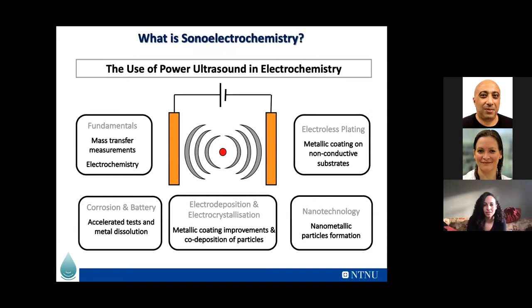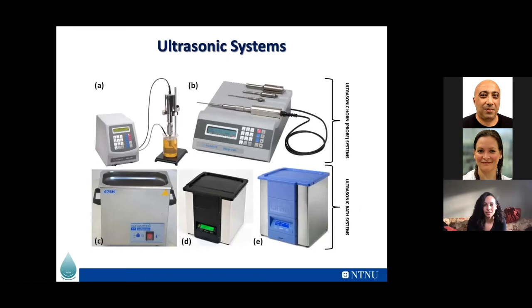There's also another area where you could use ultrasound, in electrochemical engineering and electrochemistry. For example, we looked at mass transfer measurements. You could also use ultrasound to get better plating and metal coating. It's also used in batteries, electrodeposition and electrocrystallization. I used to work in the Midlands, and we know that the plating industry and the electroplating industry was quite big. I worked with the local industry to use ultrasound to make their deposits much improved and also free of hydrogen entrapment, which is a big problem when you do electroplating or electrodeposition. Applying ultrasound to the system is, I would say, quite easy in a way.